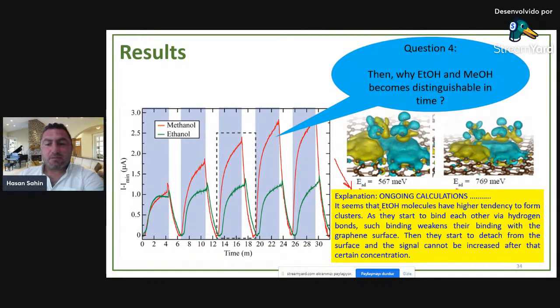It seems that ethanol molecules have a higher tendency to form clusters. So cluster formation is important. They have more tendency to form clusters actually, as they start to bind each other by hydrogen bonds. Such binding weakens their binding with the graphene surface. Then they start to detach from the surface and the signal cannot be increased any further.